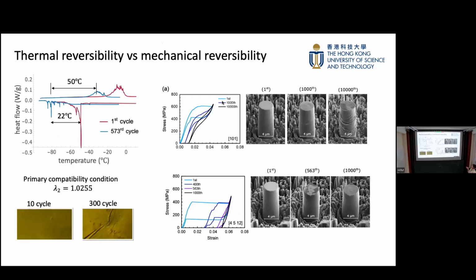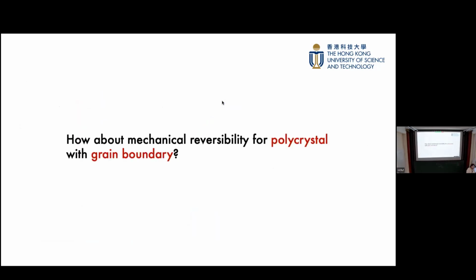We just find a coincidence: the Schmid factor is smaller, the reversibility is better; the Schmid factor is bigger, the reversibility is worse. And then let's compare this material. Here is the thermal reversibility versus the mechanical reversibility, and we find that mechanical reversibility depends on what orientation you load. And what about the grain boundary? If we have a grain boundary in the material, how would we treat this material?